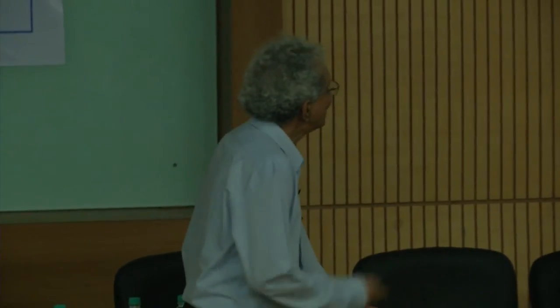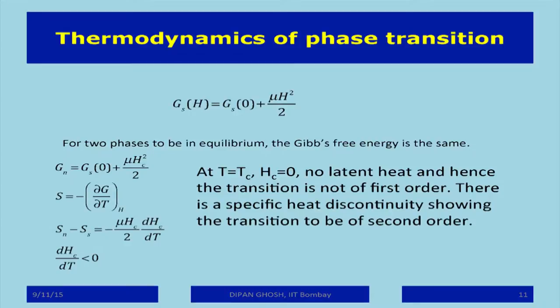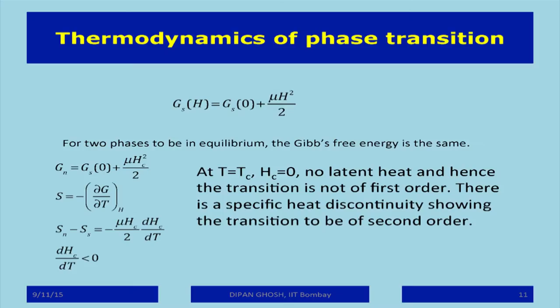Now, the other thing to notice is this, that at T equal to TC, my HC is equal to 0. So my Sn is equal to Ss, that is, the superconducting entropy is the same as the normal entropy. So as a result, there is no latent heat at T equal to TC. Since there is no latent heat, the order of transition is not a first order transition. It turns out that the discontinuity in the specific heat shows that the order of transition is a second order transition.